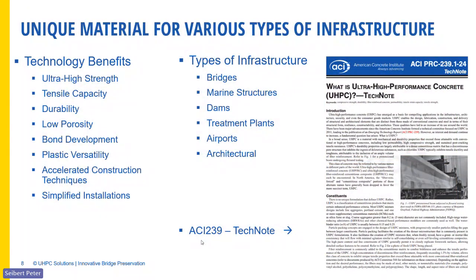So what makes this material unique? Yes, ultra high strength, tensile capacity, it's durable, low porosity, excellent bond development. So if you take, for example, and you don't design with it, but tests have shown that if you take a number 4 rebar and stick it in the UHPC and you pull at it and it's embedded for 3 inches, you pretty much break the bar every time. So it's very, very good for precast connections to design with that.